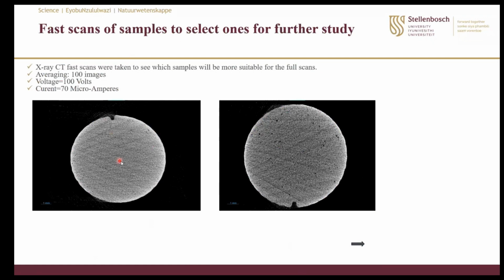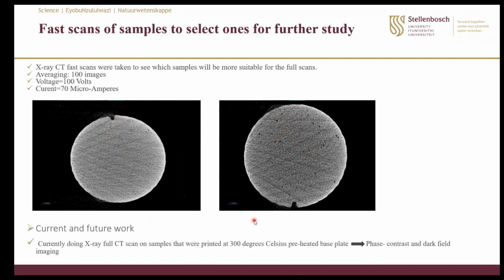What you're seeing here is the first image, printed at the preheated base plate temperature of 100 degrees. And this one is the very last sample, number 26, which was printed at a preheated base plate temperature of 300 degrees. From what I've got here, I've concluded for now that my most porous samples are the ones printed at 300 degrees Celsius preheated base plate temperature.